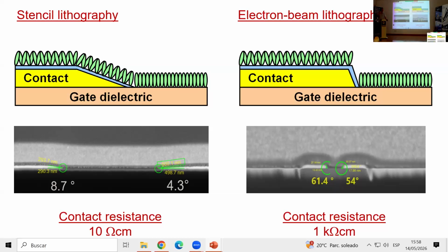So clean room, high vacuum deposition, purification of the materials. We're trying to avoid solvents, for example. You know, you introduce solvents, you get trapping, all those things. But yet, even so, we have grain boundaries, we have surface roughness, so there is charge trapping everywhere, obviously. So yeah, it's a huge problem, and it'll continue to be an uphill battle.